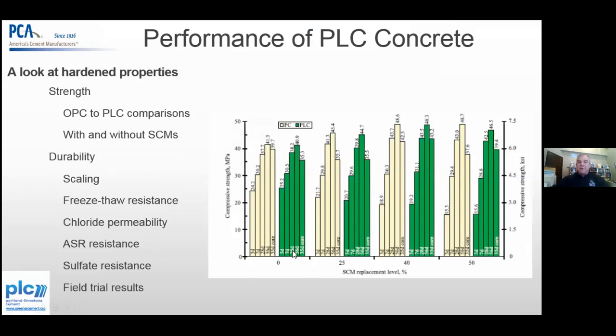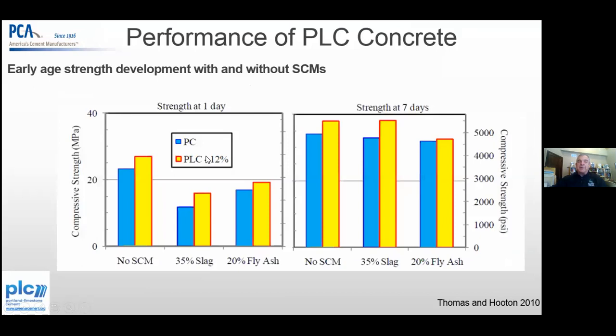But really for different replacement levels of slag, it's hard to see on this graph, but if you've got 25%, and these are in megapascals, it's a difference of 1 MPa, a 0.2 MPa difference, 2 MPa difference, half an MPa difference, at 3, 7, 28, 56, and 91 days. I think they're 91. Maybe it's something else. I can't really read that, but it's similar across the board for 0 replacement, 25% slag, 40% slag, and 50% slag in this particular graph.